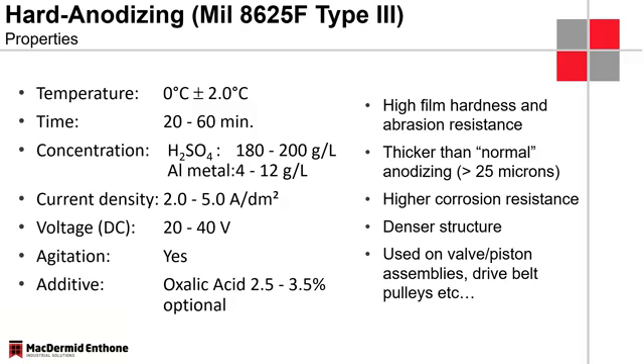The problem with oxalic acid we see is that it will discolor, or it will color the final finish. If we use it on the type 2, we would probably see a slight yellowing of the surface, which then as a final finish is not very attractive. With a hard anodizing, we'll have a much thicker layer. The layer tends to be gray to dark gray anyway, so this discoloration, this yellowing of the surface is not quite as important as with the type 2 anodizing.